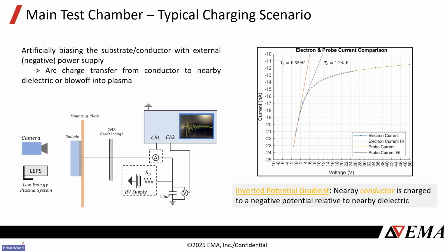What this represents in a real scenario is, say you've got a satellite in GEO. You know that if you've got a satellite in GEO, the chassis is charging highly negative. And so the conductors of your sample in that scenario would be highly negative. But once the front face of that spacecraft gets exposed to the sun, you start getting some charge neutralization of any exposed dielectrics that might be touching or nearby the chassis potential conductor. And so now that dielectric is becoming less negatively charged relative to that chassis potential, and then you start developing differential potentials that could exceed the breakdown, and you can start getting arcing behavior.